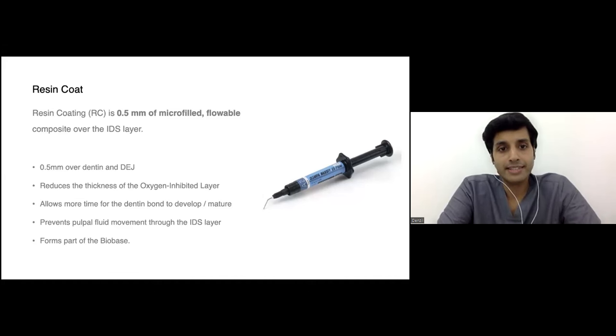We apply the adhesive. This is mainly only on dentine and DEJ. It does not go onto enamel. Enamel and dentine are never bonded together in biomimetic dentistry. It's always at different timelines. And then after we cure the adhesive, we apply 0.5 millimeters, a very thin coat, and then we spread it across the entire dentine with a perioprobe so that we know that we are not too thick. And this is what the second layer of the biobase is.